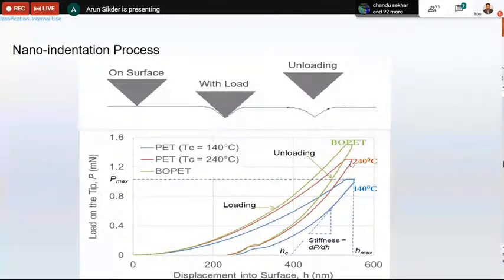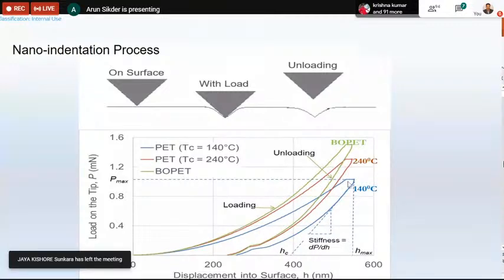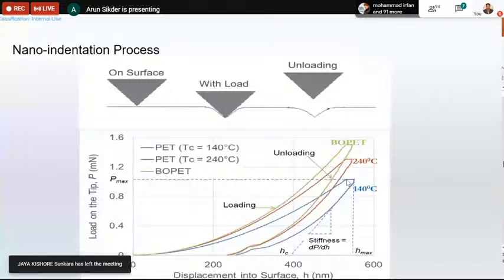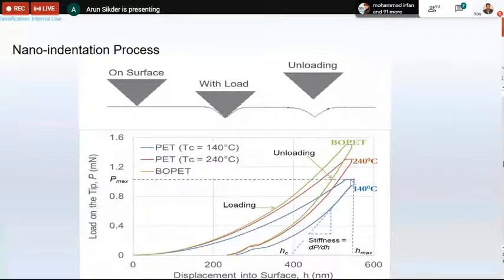These are the three different materials I am showing here. You can see these three different materials, they have loading versus unloading curves. And this is the raw data for calculating various different parameters on the surface. Suppose I go to a depth of 500 nanometers in all these three materials. Seeing these curves, the blue one, which is called PET, takes a load of around maybe 1.1 millinewton. However, BOPET takes almost 1.5 millinewton load.